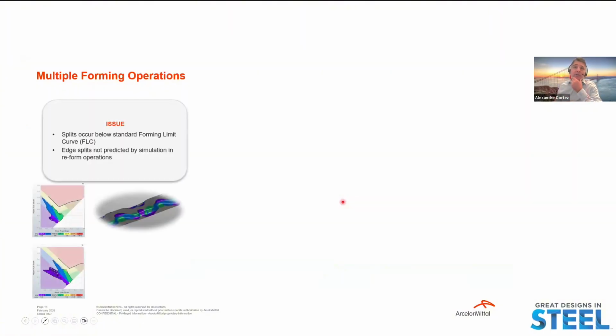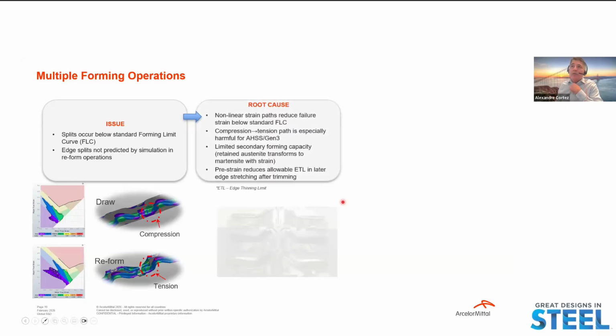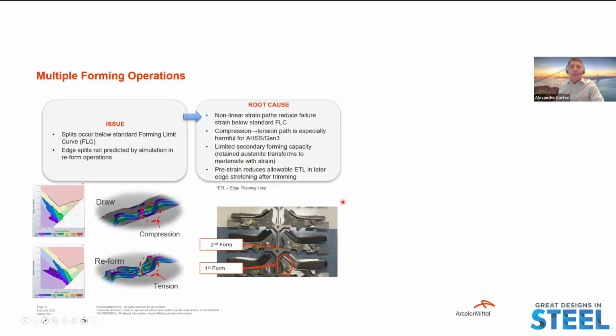And for multiple forming operations, the issue we raise is that splits occur below the standard FLC curve, and edge splits are not predicted by simulation in reform operations. As a root cause, nonlinear strain path reduces failure strain below the FLC. Compression and tension paths are especially harmful for advanced high-strength steel and third-gen products. There is limited secondary forming capacity for this kind of grades. Prior strains reduce allowable ETL in later edge stretching after trimming.